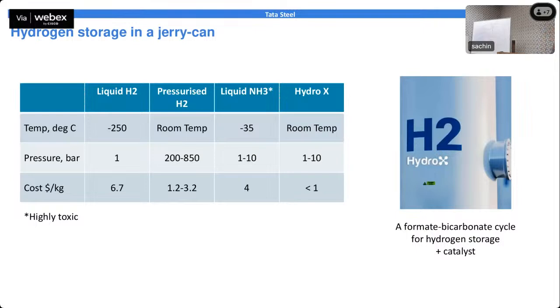The hydrogen storage, which we always miss. Today, when we think of hydrogen storage, it's either as liquid, which means you have to cool it down to minus 250 degrees centigrade and keep it there, which is expensive in energy consumption. Or pressurize it at 700 bar pressure, and keeping it at 700 bar again takes energy. Or you store it as liquid ammonia, at minus 35, better than minus 250, but still needs energy to maintain minus 35, and is extremely poisonous. In an industrial atmosphere like ours, that's a concern.